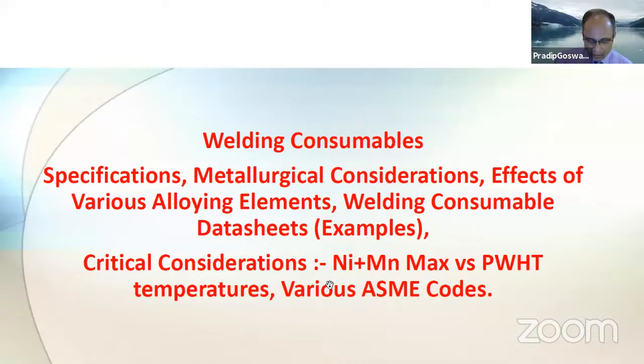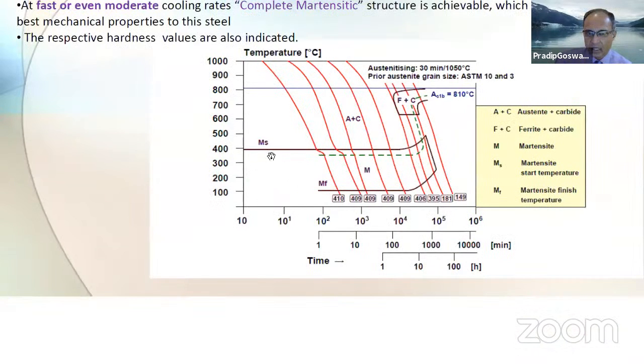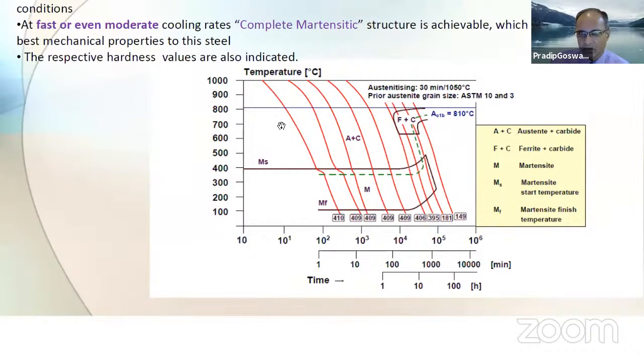Now, let's go to the next slide. Just a quick recap of it. You see here there is something called MS, or martensite start temperature, and MF, martensite finish temperature. These two temperatures are very critical for this alloy. MS for this steel is as high as 400 degrees centigrade, whereas the MF is as low as 100 degrees centigrade. And this is a typical CCT, continuous cooling transformation curve for this alloy. So that means typically from the welding temperature, which is definitely over 1000 degrees centigrade or so,